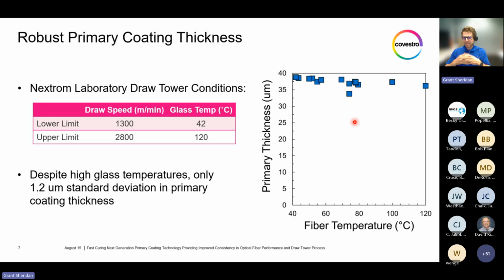We believe that the fast curing nature, the fast modulus buildup of this next generation coating lends itself to the robust coating thickness, as we're able to lock in the coating geometry very fast before the fiber temperature is able to thin the coating more and more and lead to these inconsistencies in coating geometry.